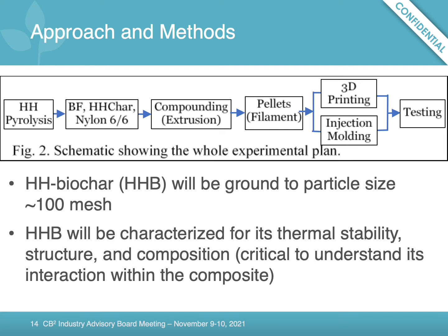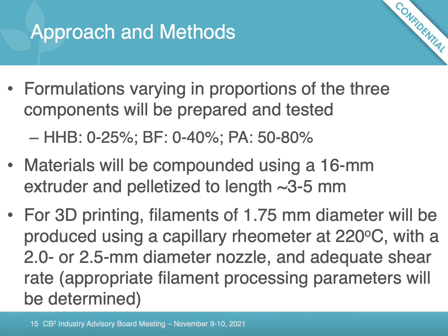We'll also make hemp hurd biochar at 3 different processing temperatures, low, medium, and high, and we'll characterize the biochar produced using these 3 processing temperatures for their thermal stability, structure, and composition. This is critical to understand its interaction within the composite with other materials. So once we determine the ideal processing temperature for hemp hurd biochar production, we will use that temperature to produce the rest of the biochar using hemp hurd, and use that in making different formulations. That is a combination of the varying proportions of the 3 components: hemp hurd biochar, basalt fiber, and polyamide, as shown here.